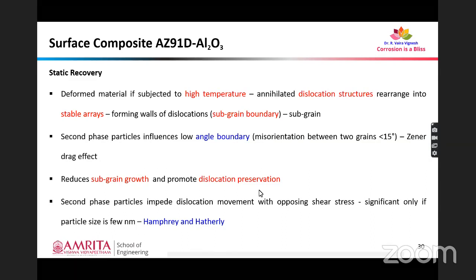Added to that, the second phase particles that we have added influence the low angle boundary. That is all because of the Zener drag effect. And the presence of second phase particles, that is nano phase alumina, reduces the growth of subgrains and promotes dislocation preservation. Added to that, these second phase particles impede the dislocation motion with opposing shear stress, and this is significant if we have a particle size of a few nanometers. So obviously, since it is nano phase alumina that we have reinforced, as per the results of Humphreys and Hatherly, these particles will impede dislocation motion with opposing shear stress, which means we'll get somewhat better hardness and strength in the fabricated surface composite.